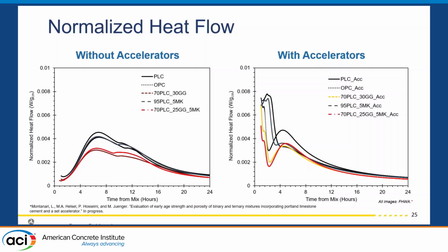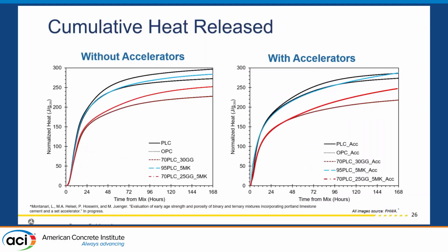And then with accelerators, the reactions are happening so quickly that we can't even see the acceleration periods. But we are seeing that our PLC, which is the highest curve there, actually has a higher magnitude of normalized heat flow compared to our OPC. So looking at cumulative heat released, we can see that our OPC, our PLC, and our PLC with our highly reactive SCM have very similar results with and without accelerators, and even more so with accelerators. So with that, we can see that we're getting a similar performance.